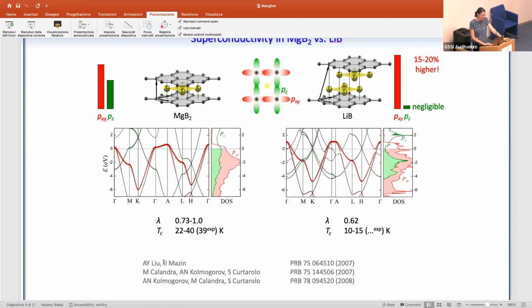At the same time, A.Y. Liu and Igor Mazin also investigated ab initio the same system in 2007. Here I just want to overview some of the key electronic structure features that were pointed out in these original studies. What was found is that lithium boron is even more two-dimensional than MgB2, and in fact has a higher density of states provided by the boron sigma states. But on the other hand, it has negligible contribution from the boron pi states.